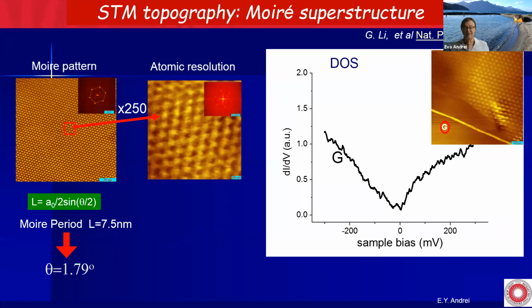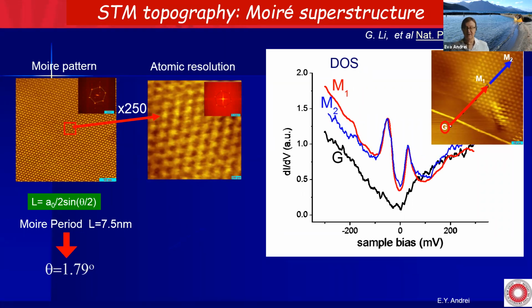So here is graphene and here is our twisted bilayer graphene. For single layer, we have a kind of V-shaped standard spectrum. We move onto this Moiré pattern and you see these beautiful peaks that appear, which we later knew were the Van Hove singularities. And no matter where we went on this sample, these Van Hove singularities were right at the same spot.